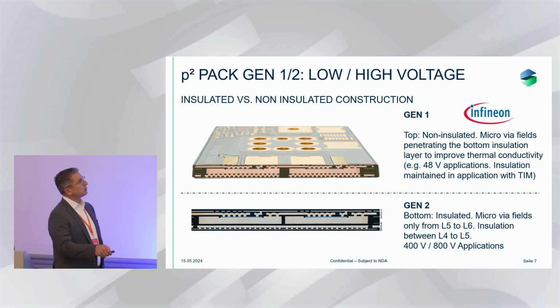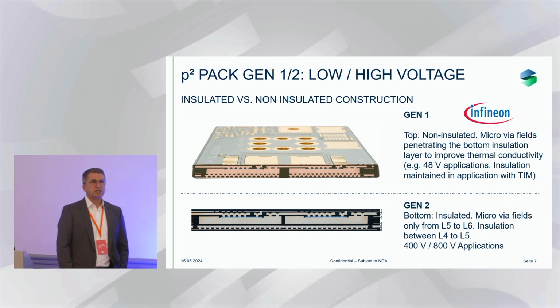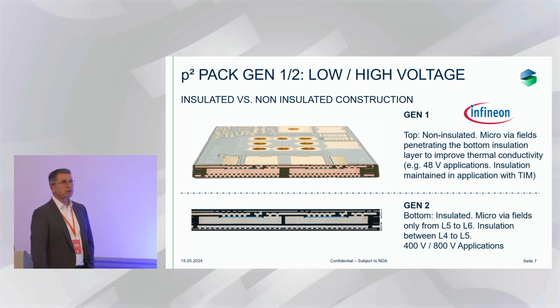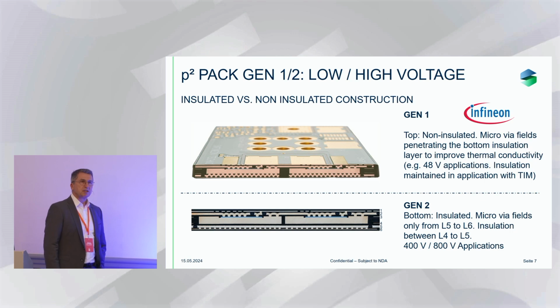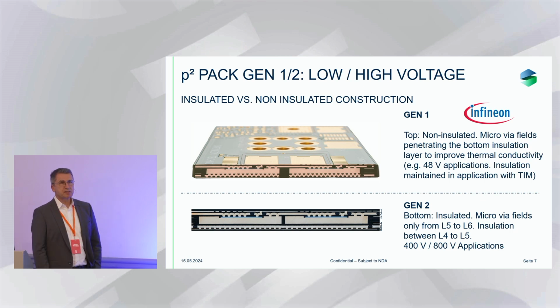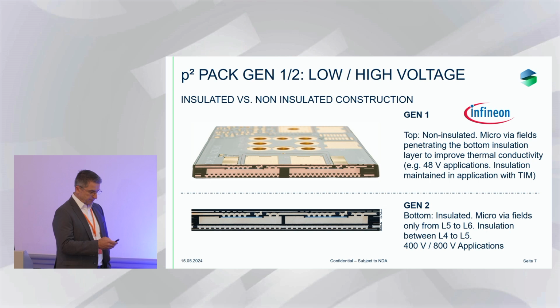And this is an insulated version. And this insulation is maintained by just leaving out one of these layers of copper-filled microvias. So we're using organic materials as insulation materials, and if you do not penetrate them, they are still insulating. These materials are special materials with an improved thermal conductivity to bring down the thermal resistance as good as possible.